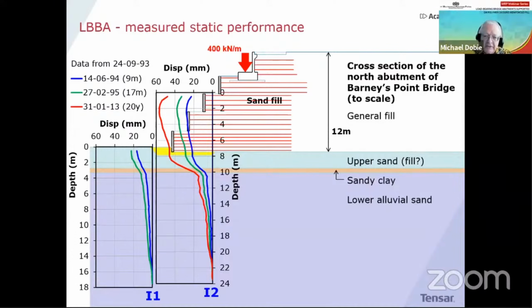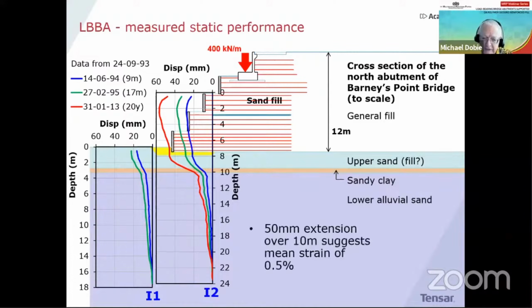Now, you might say, "Oh dear, this is a bit of a shame. The structures move forwards because of the foundation." But is it actually that serious? So let's have a look. So if we think about that piece of Geogrid, which I've just put into a sort of a bluish color, then if that particular length there at the point of the inclinometer is about 10 meters of Geogrid, and we assume that the buried end doesn't move, then that 50 millimeter extension at that point, let's say from the red line, is a mean strain of about 0.5%, very close to the target given in BS 8006.